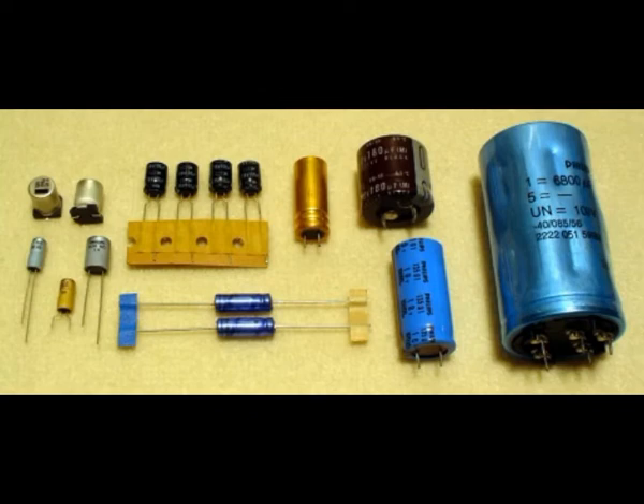This rating is tested with an accelerated aging test called an endurance test, according to IEC 60384-4-1 with rated voltage at the upper category temperature. One of the challenges with this aging test is the time required to extract any meaningful results. In response to demands for long life, high-temperature performance from automotive and green energy applications, solar microinverters, LEDs, wind turbines, etc., some capacitors require more than a year's worth of testing, 10,000 hours, before they can be qualified. Due to this limitation, there has been increasing interest in methodologies to accelerate the test in a manner that still produces relevant results.